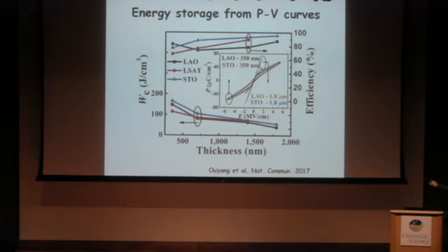Actually, they're not. If I enlarge them, you can still see the ferroelectric loop. But they're very, very slim. So the energy density, of course, the highest is for the thinner film, which you can apply higher field. Is about 170 joule per cubic centimeter. And the thicker film actually have an efficiency close to 100. Actually, the best record we got is 96% of the film grown on strontium titanate.